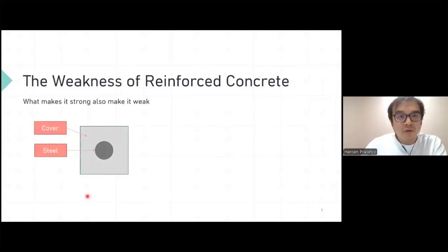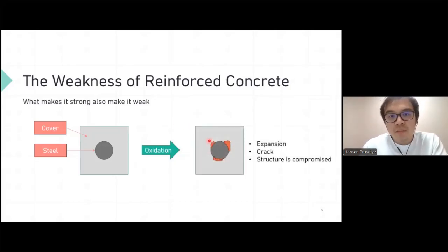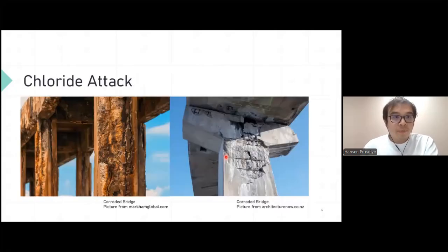Because, for example, look at this cross section of a concrete prism with a steel bar in it and a concrete cover. The problem with the steel bar is that oxidation happens, and then it starts to corrode. Some rust appears, and then expansion happens, cracks happen, and then the structure is compromised. The effect of chloride attack can be severe, as you can see in these pictures. When it gets to this level, the structure is no longer suited for use. So if before those colosseums lasted for thousands of years, now it only lasts for maybe 100, maybe less.